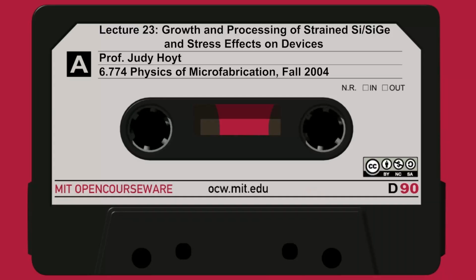What happens is this lattice, this cubic silicon germanium, wants to be cubic. It wants to be larger in equilibrium than silicon, and you're squeezing it, though. It turns out, again, if the layer is thin enough, it's energetically favorable for the in-plane lattice parameter of the material that you're growing to match that of the substrate. So the silicon germanium is squeezed in X and Y, and it pushes up in Z. This layer is what we call strained silicon germanium on relaxed silicon, and it's under biaxial compression. It's being compressed in the XY plane.